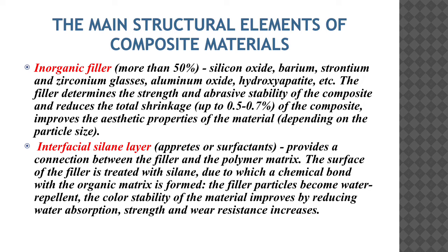Inorganic filler, more than 50%, consists of silicon oxide, barium, strontium, and zirconium glasses, aluminum oxide, hydroxyapatite, etc. The filler determines the strength and abrasive stability of the composite and reduces the total shrinkage to 0.5-0.7% of the composite. It improves the aesthetic properties of the material depending on its particle size.